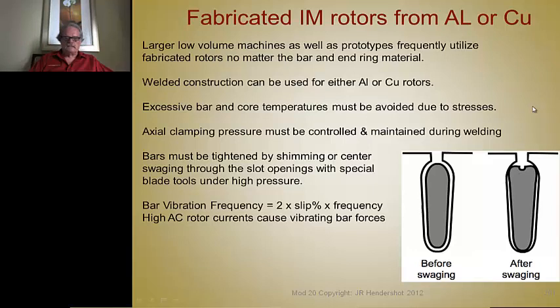Now that's a laborious, one bar at a time, horrendous thing to do, but it must be done in large machines. The high-speed machine tool spindle people, they don't do this. They fill this full of a silver brazing paste, and when they're brazing the bars to the end ring, they fill the slots in the rotor with the same paste. So they stick this in an oven at 1500 degrees for an hour, and it silver solders the bars in place to the core. It works very well. All high-speed grinders and a lot of machine tool spindles use this technique.